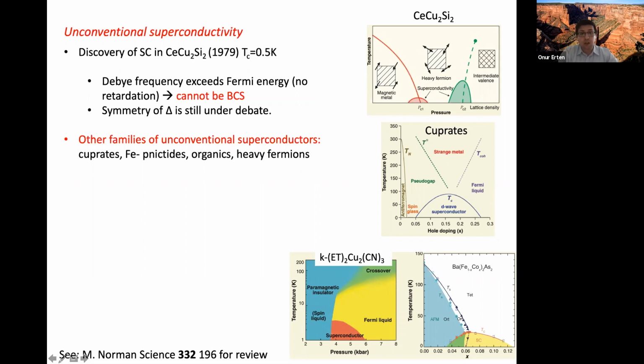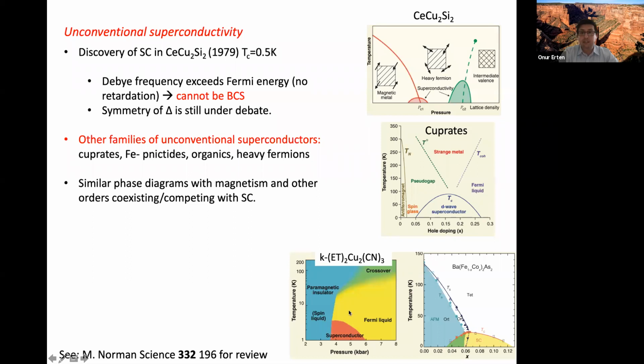So I discussed why they cannot be BCS, but when you look at the phase diagram of these systems, you can see that they are very similar to each other. You usually have some kind of magnetic order. In the case of cuprates, at the parent compound, when there's no doping, it's an antiferromagnetic Mott insulator. Whereas in heavy fermions and iron-based superconductors, it's usually an antiferromagnetic metal. And it can be a ferromagnetic metal too. In the case of heavy fermions, there are ferromagnetic superconductors as well.